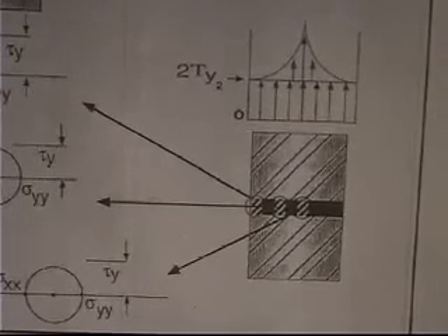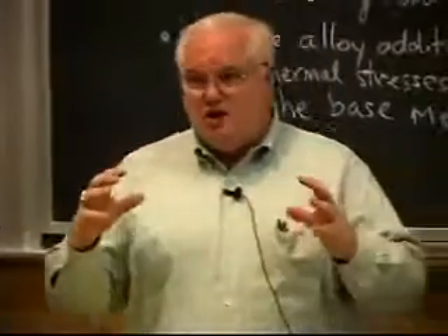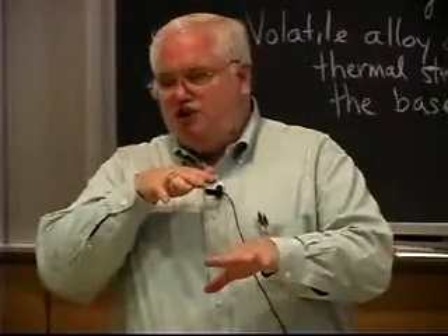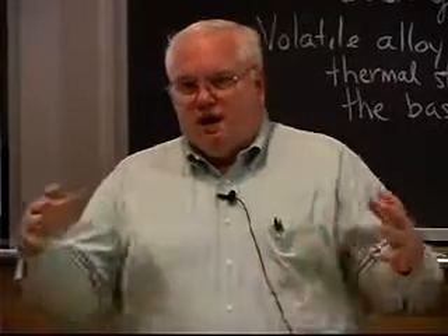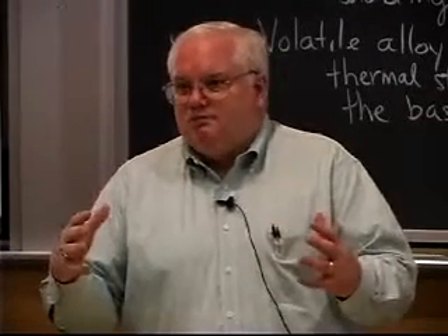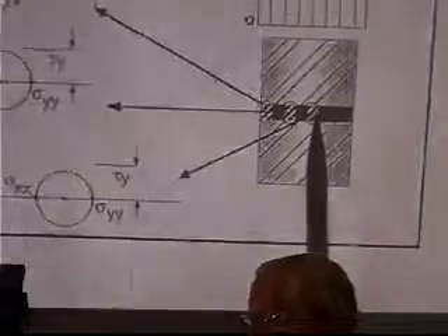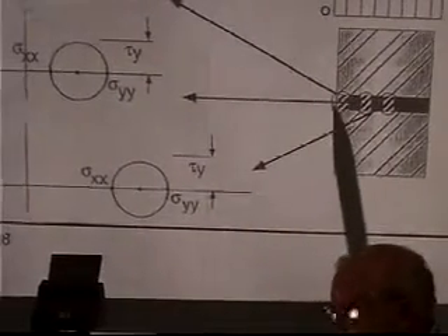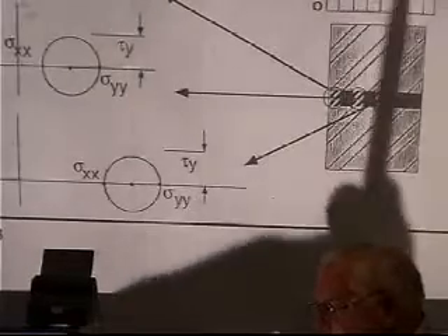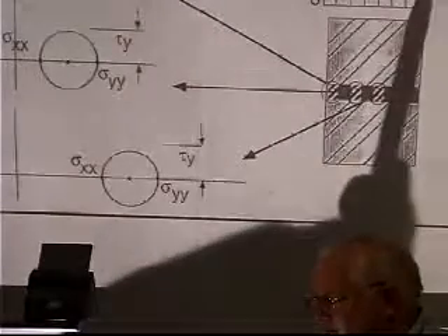Now, it turns out if a material is under hydrostatic compression or tension, it doesn't yield, because a metal yields by shearing along its shear planes, and a hydrostatic stress doesn't produce any shear. There's absolutely no shear. I'm sorry, shear is on the vertical axis. The principal stresses, or the hydrostatic stresses, are where the shear stresses are 0. So this is the hydrostatic component along this horizontal axis. And as I go in towards the center, I get a larger and larger hydrostatic stress, or sometimes it's called a triaxial stress. I have a very high triaxial stress in the center of this joint. It decreases over towards the edge. And that gives me an actual local yield strength of the soft material that goes like this, not like that.